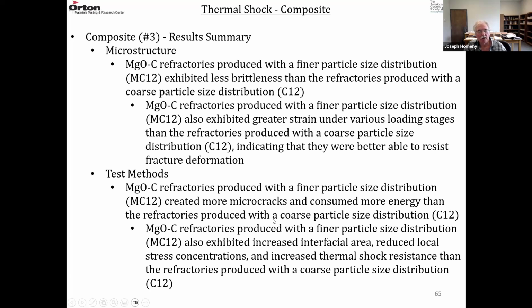So by changing the particle size distribution, it changed the fracture path, the fracture mode, to one that consumed more energy during fracture. It redirected the crack along the matrix particle interfaces and through the matrix.